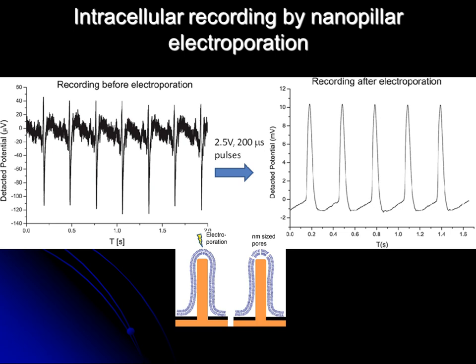After electroporation, we see a huge change. The left and right image plots are recorded by the same electrode on the same cell. Before electroporation, we see a small signal and also a biphasic shape. After electroporation, it becomes an intracellular recording. It's monophasic, only upward. A lot of details can be seen, such as changes in the resting membrane potential, the overpotential, and the shape of the action potential. And this is a huge advantage because our electroporation is very gentle, as I will show later. And the fact that we can switch the nanoelectrode from extracellular recording to intracellular recording is also a big advantage.